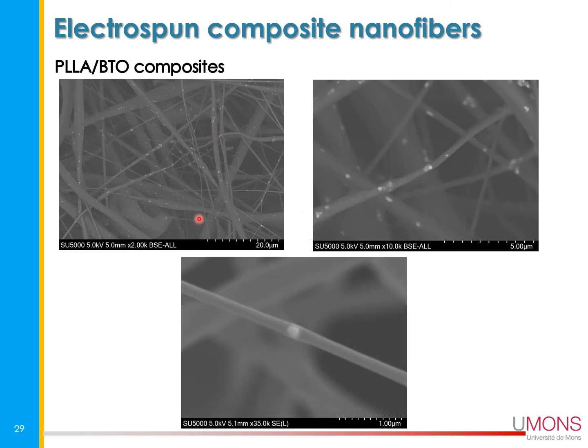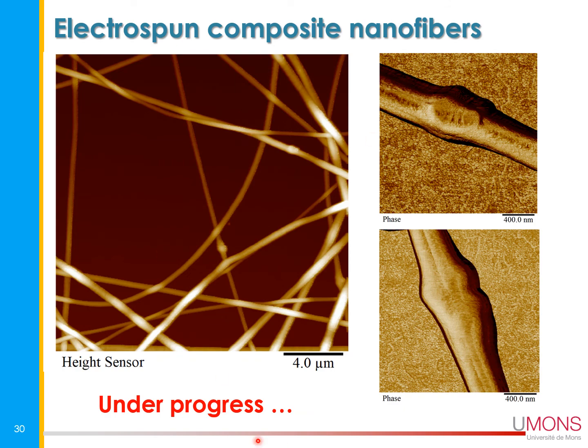So this is some SEM picture of those PLA BTO composites, and we can see that there are a lot of small grains corresponding to the BTO nanoparticles. This is the work done by Kyung as well. So this is what we have now with the tapping mode, and you see that from the mechanical properties, it's impossible to see a difference between the BTO and the polymer, because most probably the BTO is just embedded in this nanofiber, and it's homogeneous here. The idea is to see if the incorporation of BTO nanoparticles into the fiber will increase or not the piezoelectric properties that we are aiming at measuring and using for devices.